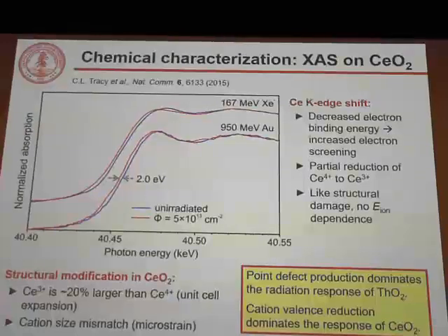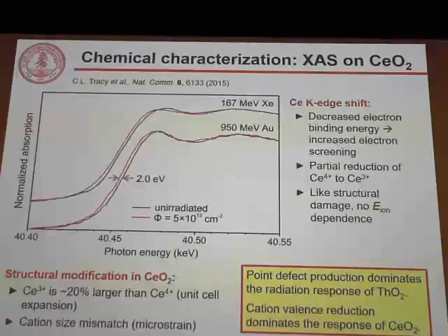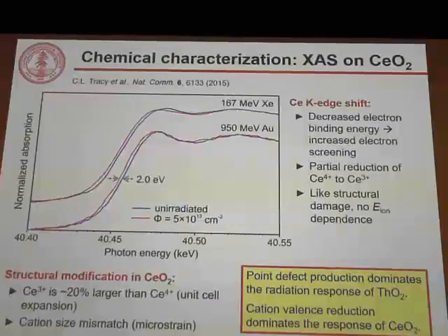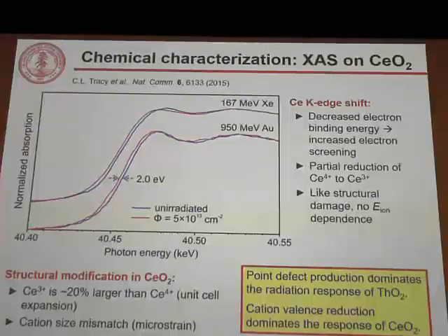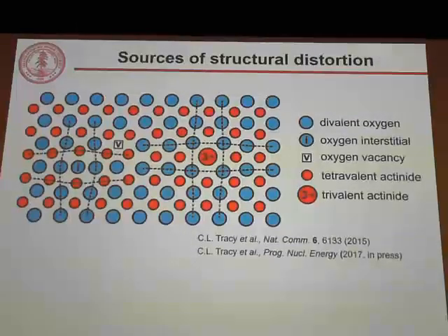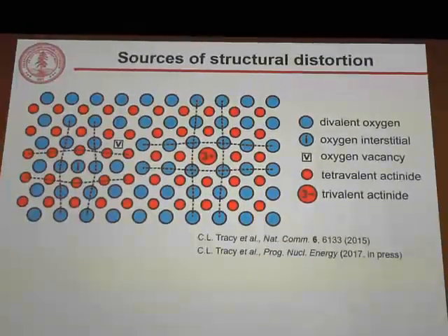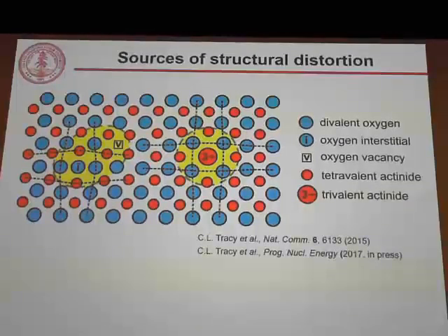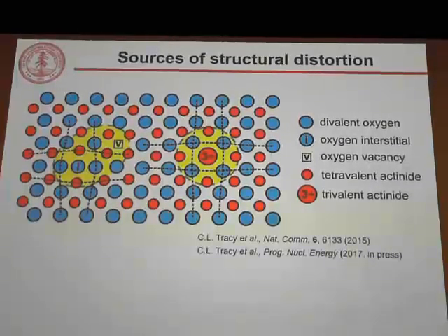So from this, what we can conclude is that in thorium dioxide, damage is due to a typical defect production mechanism, the displacement of atoms forming point defects. Whereas we have a very distinct cation valence reduction process that dominates the radiation response of cerium dioxide. So here, schematically, I summarize these two modes on the left and right. On the left, we show a typical or conventional defect production damage mechanism. On the right, the same structural distortion, similar damage from this redox mechanism.